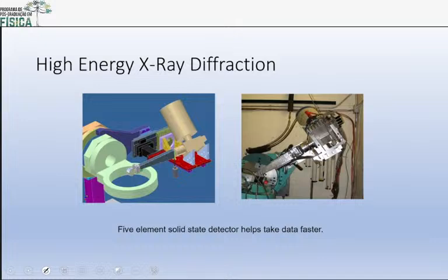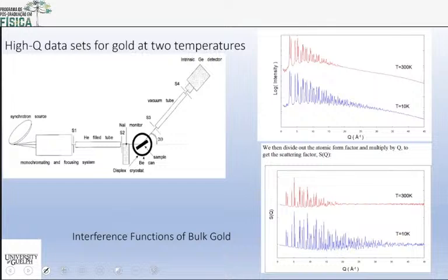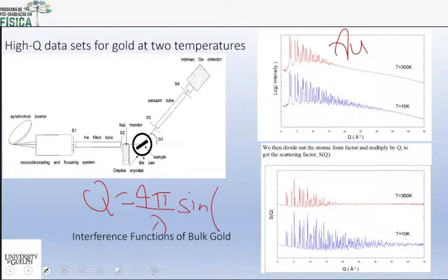We have an apparatus here like this, and here's the model, and here's the real thing on the right side. Here's a picture from a publication long ago. Here on the right, I'm going to show you our original data. So what I'm measuring here is gold, Au. And we measured this intensity as a function of momentum transfer, Q, okay? Q is equal to 4 pi over lambda sine of the scattering angle, 2 theta over 2. And when you plot it this way, this is the pattern you get.